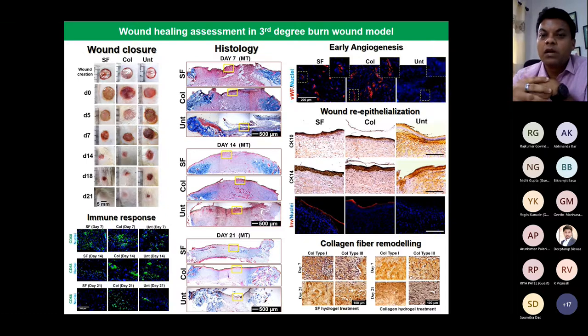And if you look at the wound re-epithelialization and the different layers, you can see cytokeratin 10, 14, and you can see a very thick layer of that being formed. In comparison to collagen, it is equivalent, or even sometimes better. That gives us a lot of confidence that this is an alternative wound care product, which can regenerate the wound site and take care of wounds at a very early healing stage, not only chronic, acute, but diabetic wounds.